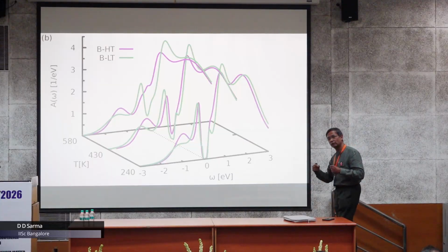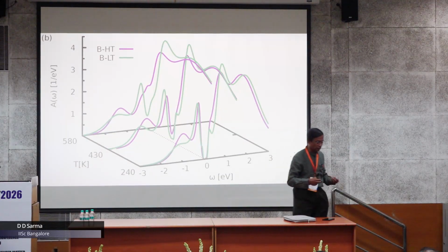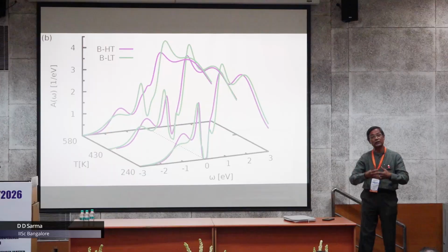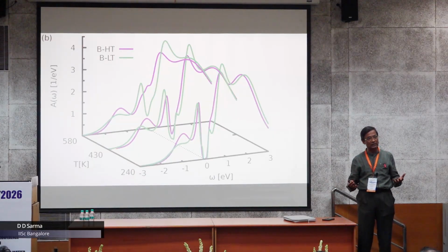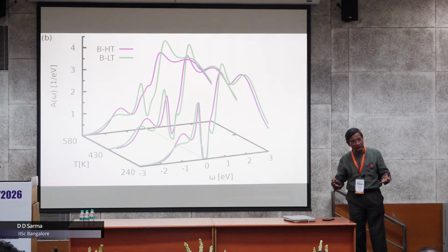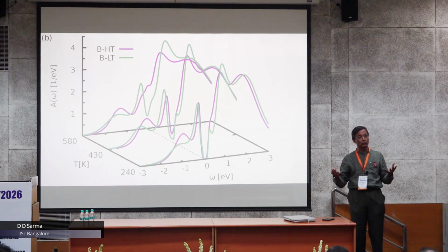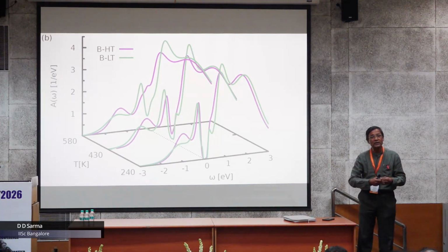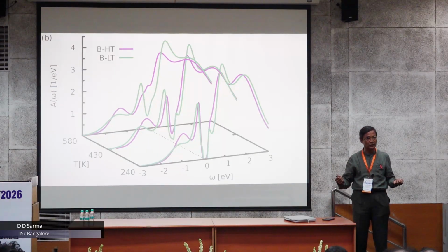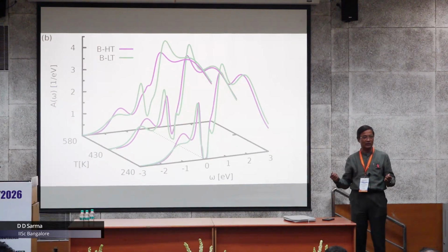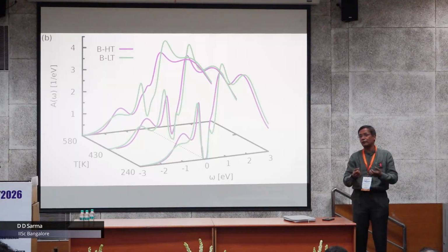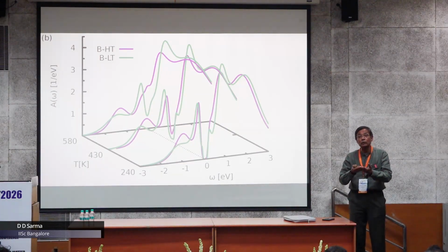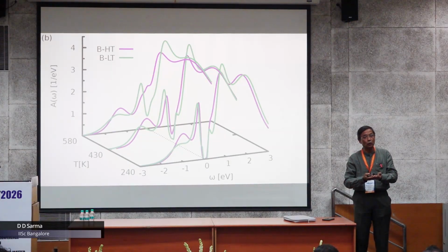But DMFT can be done for different temperatures. So I can do the calculation for different temperatures, including the electron excitations and what it does to the electronic structure. Of course, if you take any insulator and do a finite temperature calculation, no insulator is insulating at finite temperature, simply because there's this very boring thermal excitation of electrons across the gap. So there is a certain number of free electrons and holes available, there's some conductivity, and that fills up the gap, it becomes non-zero. So we like to know what happens at zero temperature to be able to define whether the system is insulating or metallic.